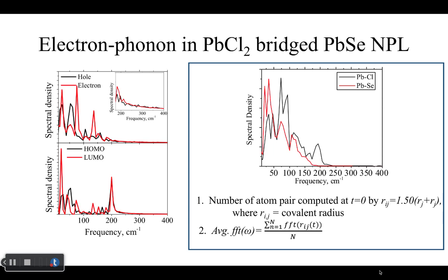So in this case, I consider the diameter as the covalent bond diameter of the atoms. Previously, I calculated with the van der Waals diameter of every type. I thought you just take the difference between the coordinates of each atom. No, I mean how I define the bond. If the distance between these two atoms is less than 1.5 times the covalent diameter of that bond, then I consider that as a bond.